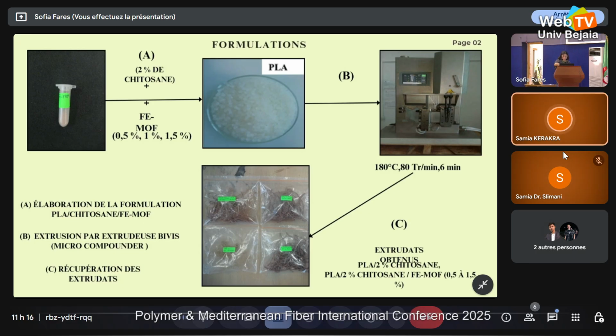The first one, PLA with 2% Chitosan with the MOF only at different loadings: 0.5, 1, and 1.5. And the second series was PLA with 2% Chitosan, and this time with different contents of our composites: 1, 2, and 3% with a 1:1 ratio.